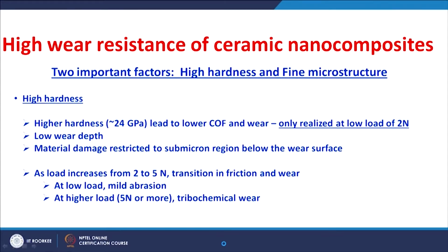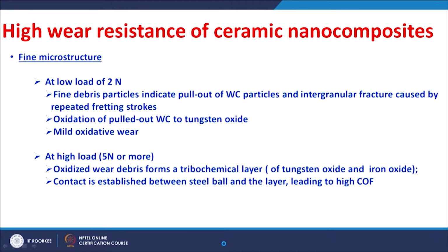whereas at higher load, as the load is increased from 2 to 5 Newton, there is a transition in the friction and wear. At lower load there was a mild abrasion, whereas at higher load, that is 5 Newton or more, tribochemical wear dominates. With respect to the finer microstructure obtained by spark plasma sintering for these nanoceramic composites, at the lower load of 2 Newton you found fine debris. The fine debris particles necessarily indicate the pull out of tungsten carbide particles, and once these are pulled out, they are subjected to fracture. These are caused by the repeated fretting strokes, and these pulled out tungsten carbide particles are in the contact where the fretting is continuing in ambient conditions.